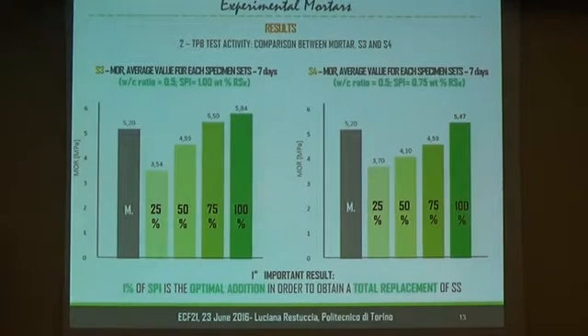In order to obtain a proper mix design, we decide to use the recycled washed sand, lowering the percentage of superplasticizer addition. In series 3, we add 1% by weight of superplasticizer. In series 4, we add 0.75% by weight of superplasticizer of recycled washed sand. In these two cases, we obtain strange results. In fact, as you can see, for lower percentages of replacement, we obtain a decrease in terms of modulus of rupture in series 3 and even in series 4.